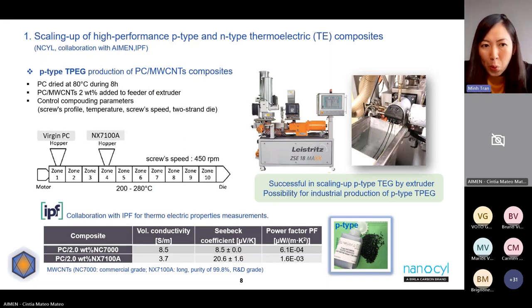thermoelectric generators. At NCYL, a lot of work has been done to optimize all of the parameters for the extrusion, with the recipe transferred from our partners AIMEN and IPF for the P-type grade of polycarbonate and multi-walled carbon nanotubes. We optimized the temperature in the different zones of the extruder, the throughput, the screw speed, etc. Finally, we succeeded in scaling up the P-type thermoelectric generator by extruder, and we have the possibility of industrial production of this P-type.